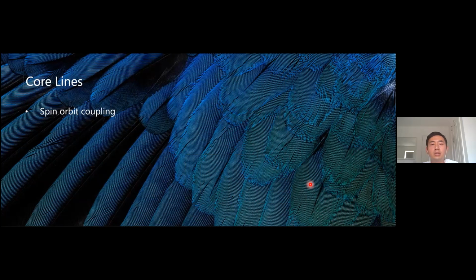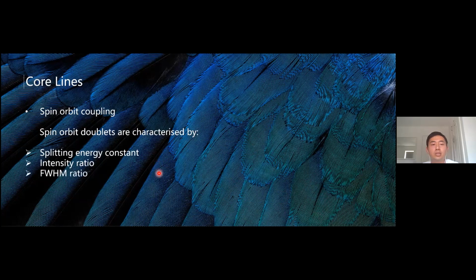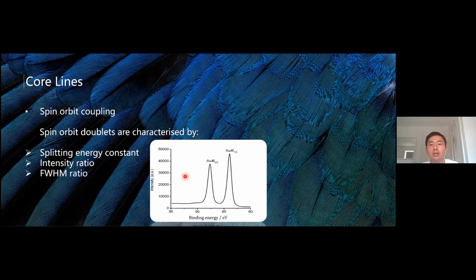The spin orbit doublets are characterized by splitting energy constant, intensity ratio, and the full width at half maximum ratio. For example, the gold 4F, we saw that they always appear as doublets, and the certain distance never changes. And the ratio between these two is 4:3. And the full width at half maximum is always the same.